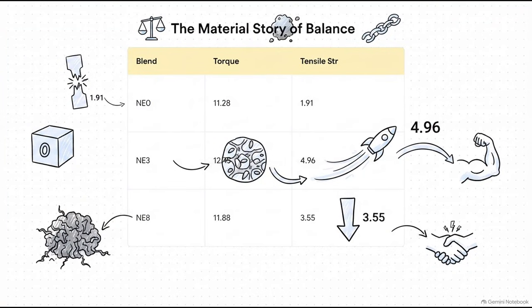The raw data tells the story of this crucial balance perfectly. Our baseline rubber with zero metal, Ne0, has a tensile strength of just 1.91 megapascals. But look at our Goldilocks blend, Ne3. The torque, which measures how well the network resists deformation, jumps up to 12.45, and the tensile strength literally skyrockets to 4.96 megapascals. It is vastly stronger.